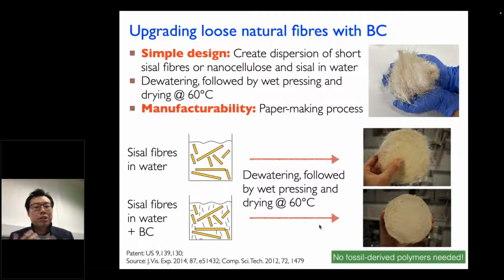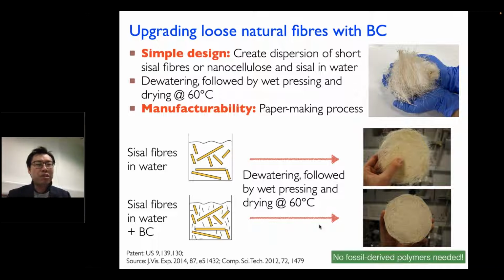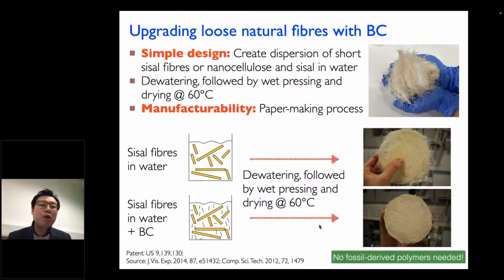Now, we can also look at using nanocellulose and that hydrogen bonding formation to bind loose fibers together. The design is that you disperse nanocellulose with bigger fibers, remove the water, press them, the nanocellulose binds together, forming these irreversible hydrogen bonds, ultimately producing a fiberboard. Now, these fiberboards do not need any glue. You have nanocellulose, and in this case sisal fibers or any other fibers you can think of, put them together, press them out, you get a very rigid board.